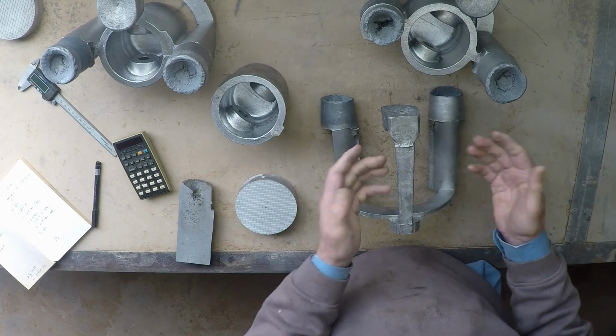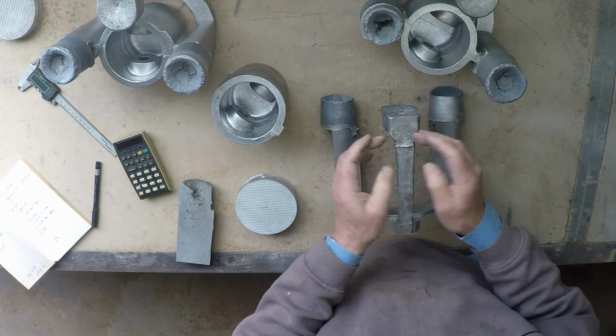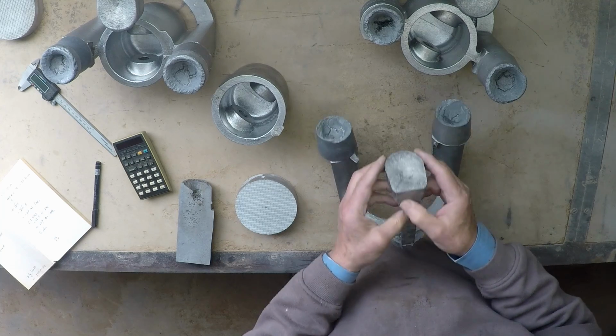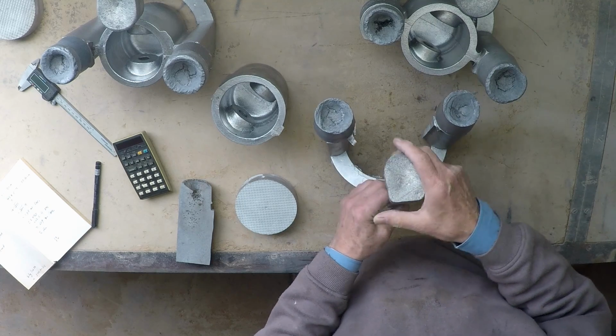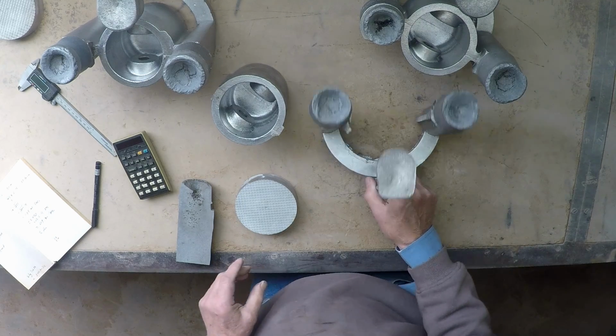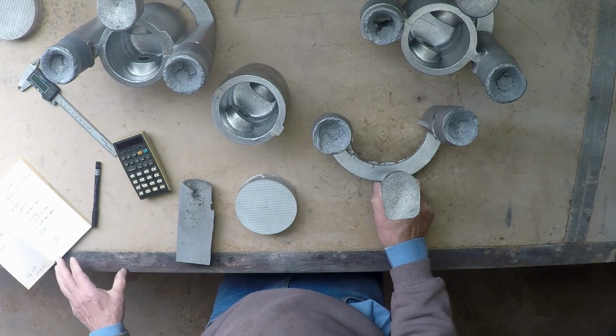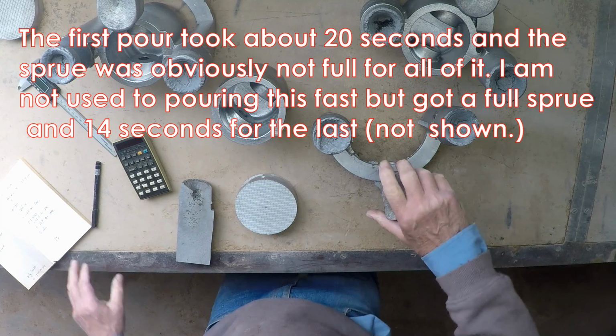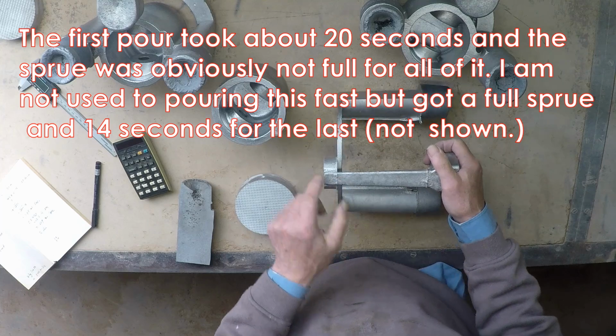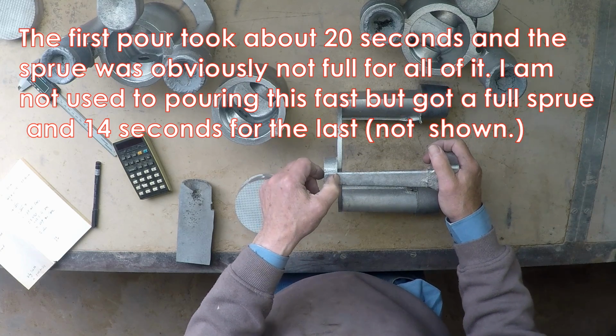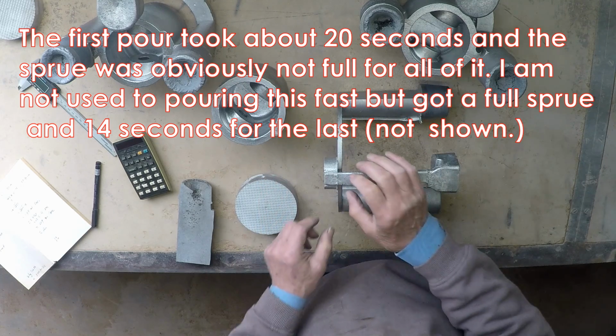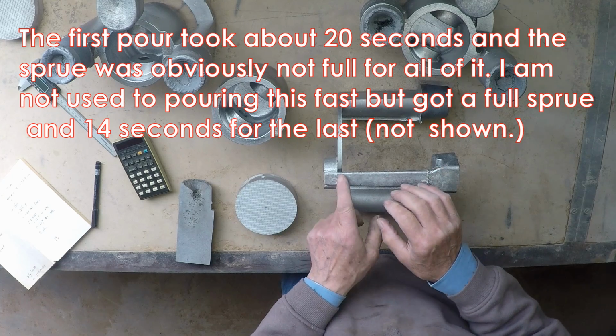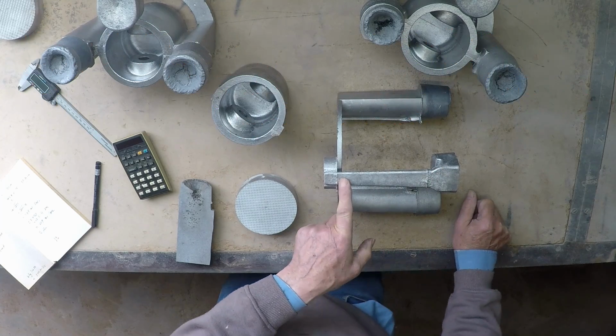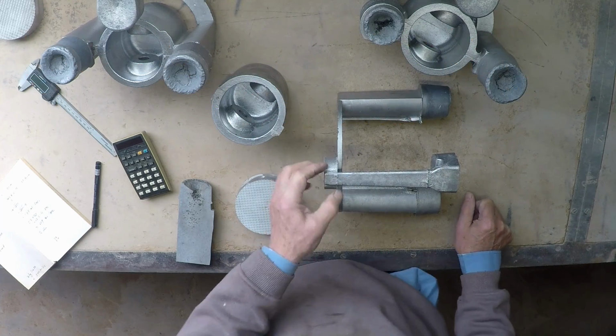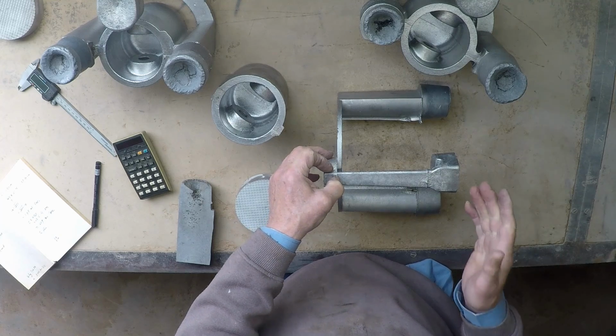This sprue, and you may have noticed when I poured, I commented that I really couldn't keep this pouring basin full because we figured the sprue was a bit big. It took 14 seconds to fill this casting, and if you calculate the flow down the sprue, it should have hit the bottom at, as I say, 2 meters a second, and with that area, that would give us about 600 grams of metal passing there every second.